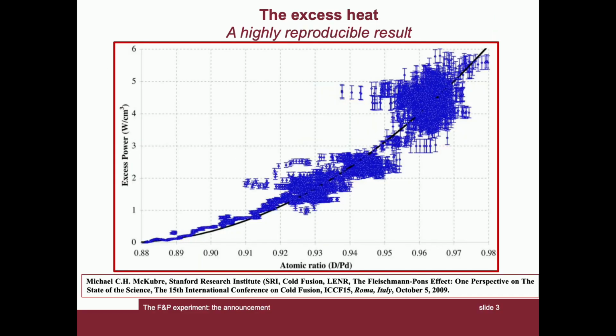The excess heat. The most significant evidence of the experiments performed over the years on the model of those of Fleischmann and Pons is that the excess power measured increases as a function of the deuterium-palladium ratio in the various electrolysis cells tested. The data are substantially connected in a curve that grows almost exponentially.